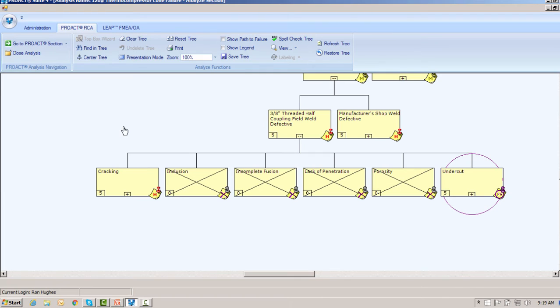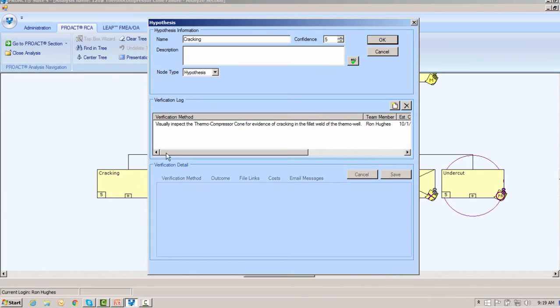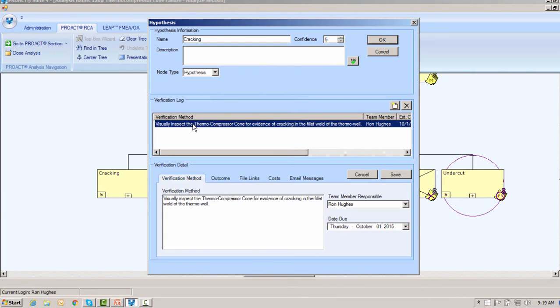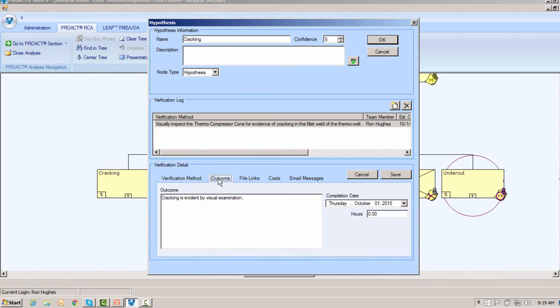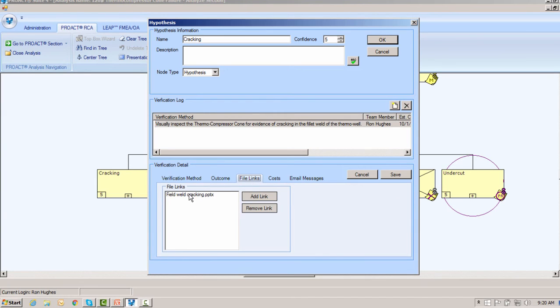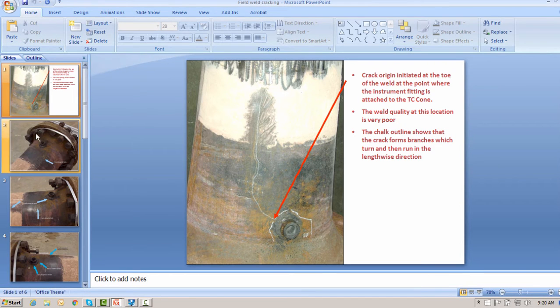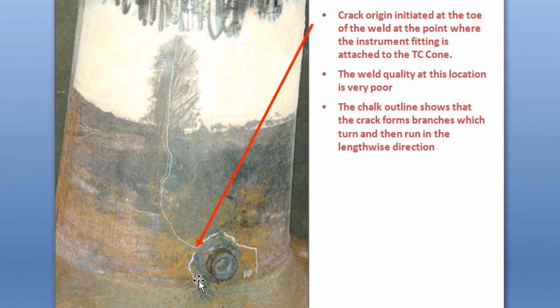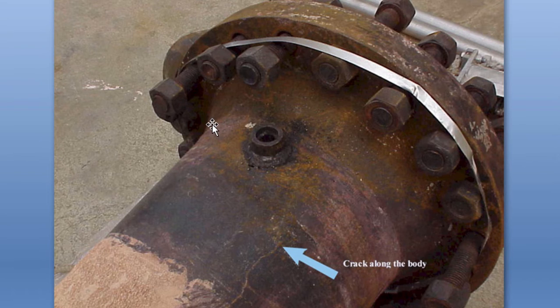Now I really don't need an RT to see the crack. I verify it by visual examination. The outcome is that cracking is evident by visual examination. And if we look at it, we can look at the crack closer. And here you can see it. Now aesthetically, this is a very ugly weld. However, it is fully fused and it is fully penetrated. So it should have held. It didn't hold. So we're going to have to account for that.